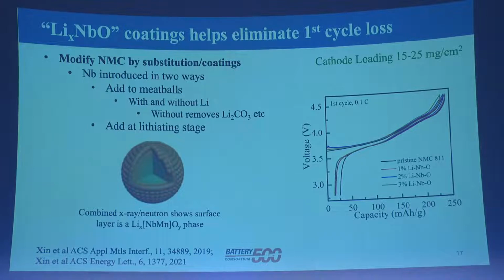What surprised us, the surface coating isn't a lithium niobium oxide. Turns out it's a lithium niobium manganese oxide. So some of the niobium goes into the lattice, ejects some of the manganese, which then forms this protective coating. And I think you can see here, we've got back about 50% of this loss. We think if we optimize this, we can probably get all of it back. So that'll be a big saving. But it's these little things that can get us, say, from 250 to 300 to 350 to 400 watt hours per kilogram in commercial batteries.